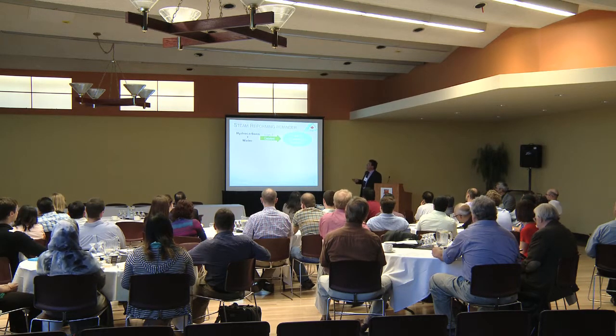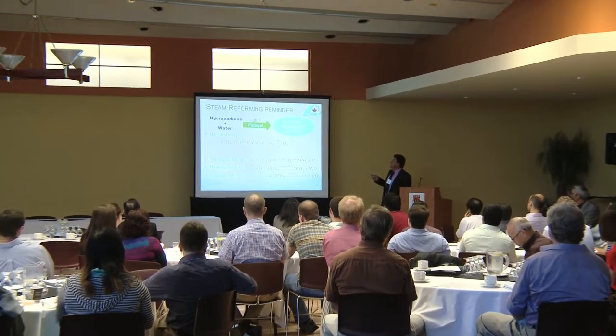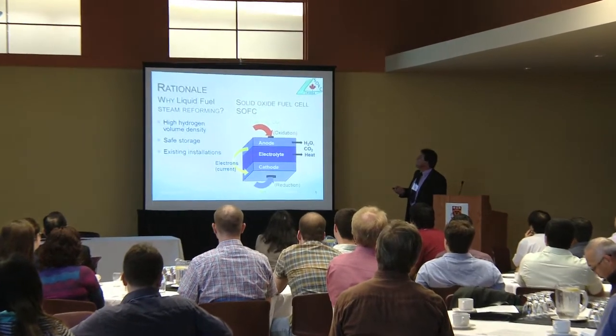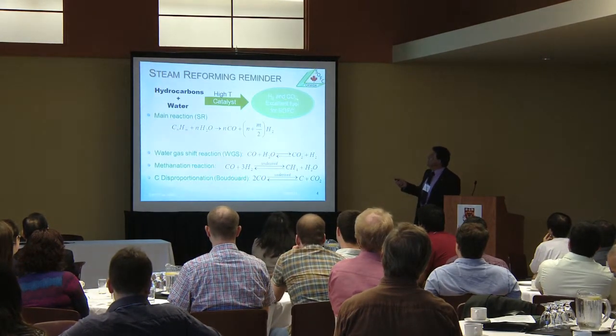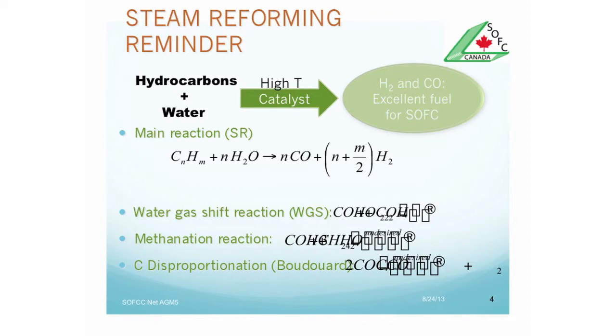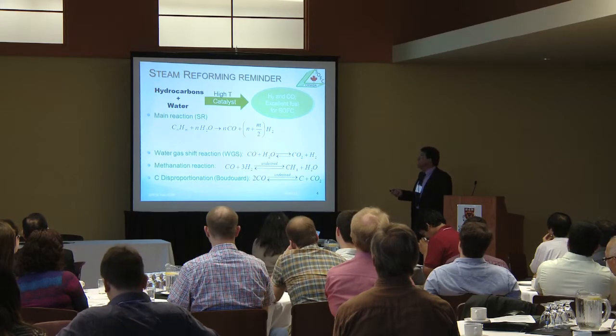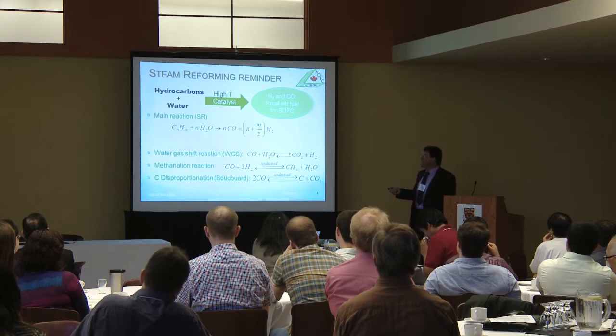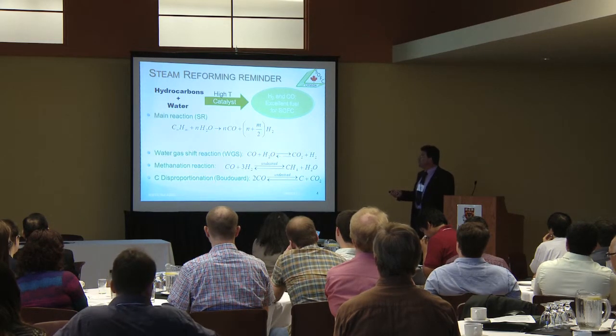So, steam reforming reminder, I will go fast on this. We have hydrocarbons and water, high temperature and catalyst, and we produce a mixture of synthesis gas, which is essentially hydrogen and CO. The main reaction is this one, and there are side reactions, desired and undesired. The water gas shift is essentially desired when we want to decrease the amount of CO and increase the amount of hydrogen, used mainly for other types of fuel cells. In the case of SOFC, it's not so important.